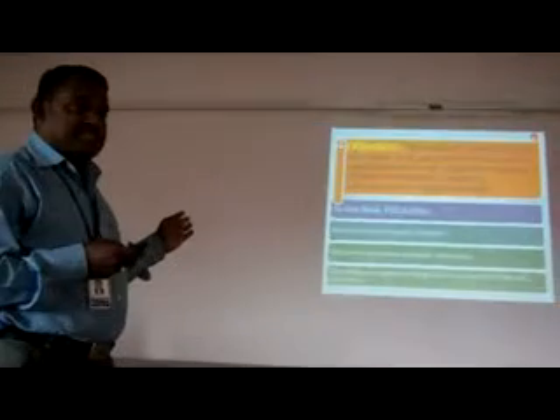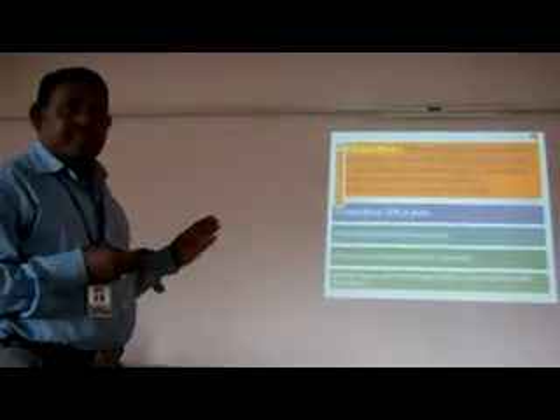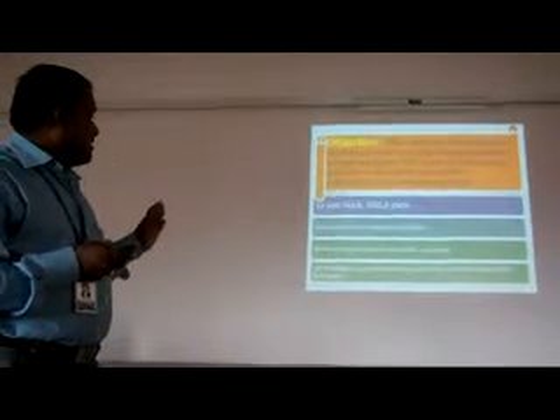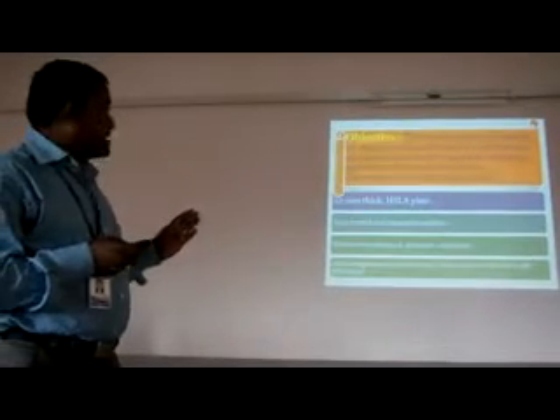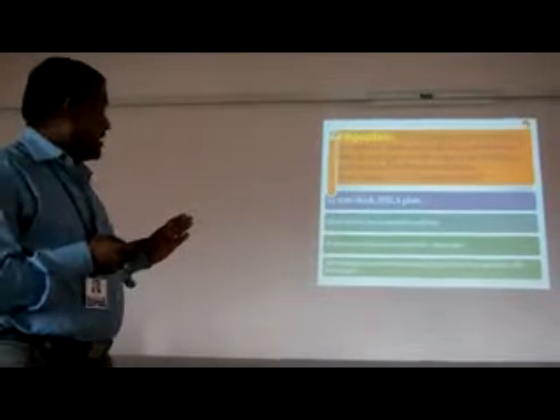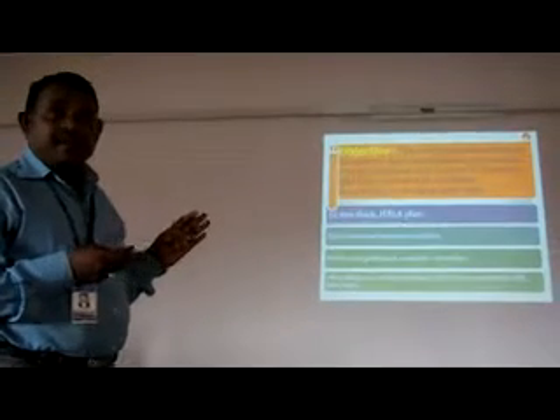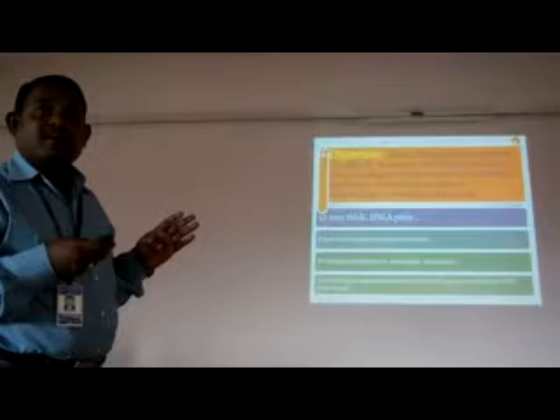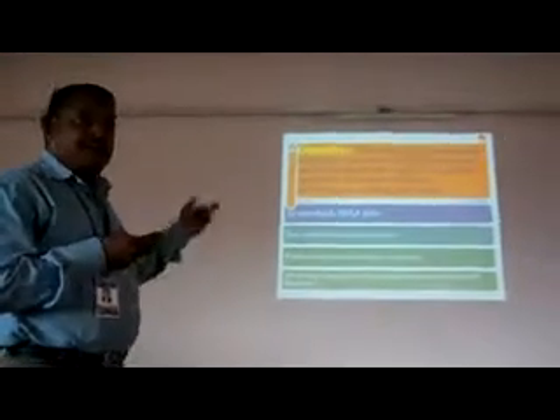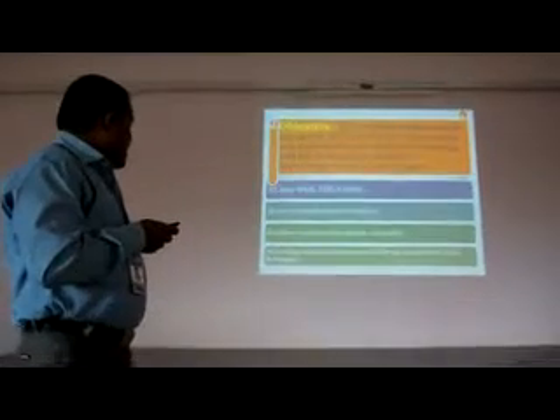For this investigation, they took 12 mm thickness HSLA steel plates, heat-treated, that is quenched and tempered, and the welds were performed with austenitic stainless steel fillers. Normally, the quenched and tempered steel is welded with austenitic stainless steel filler because the base material offers very high strength of about 1300 megapascal. It has to be welded with a quite tough weldment. That is the reason these are welded with austenitic stainless steel fillers, and all welding was performed using the GMAW process.